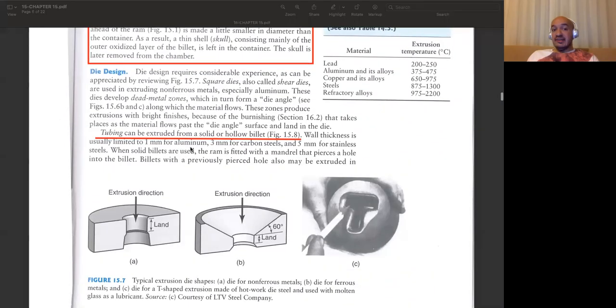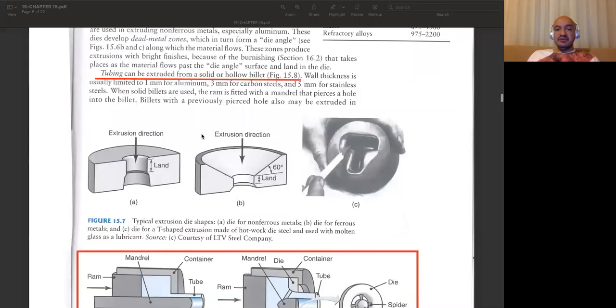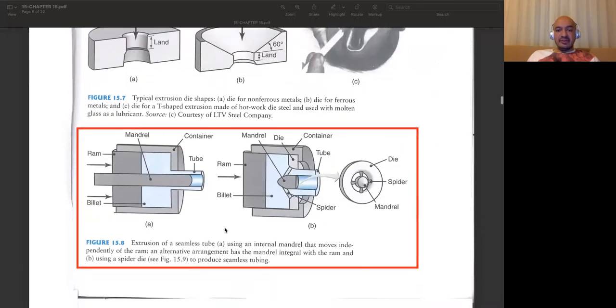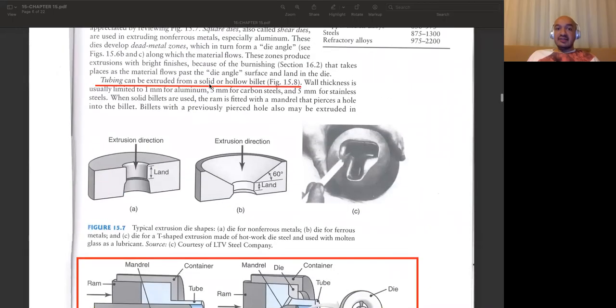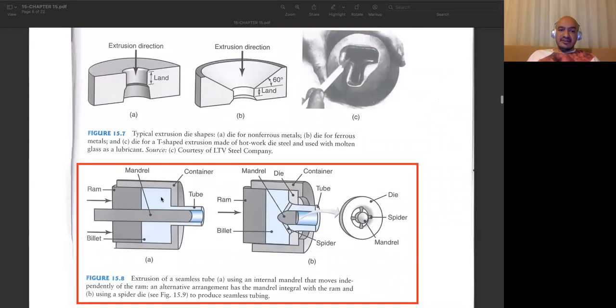And furthermore, with this process, we can even produce tubes. What we need to do, we may use some mandrels, and we can do this process by using solid or hollow billets. This is a hollow billet, as you see. The center of your billet material, the workpiece, is empty. We have an opening there, so we push our mandrel into that. And since there's a clearance between the mandrel and the die walls, once we apply force from this left side, we will be producing a seamless tube.